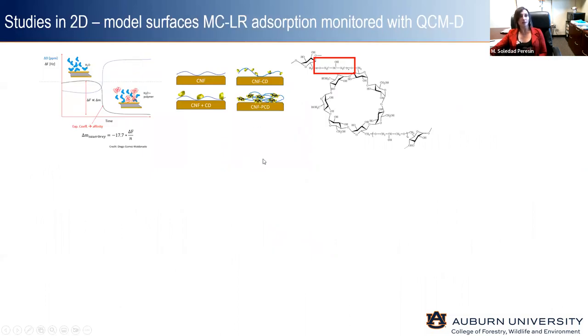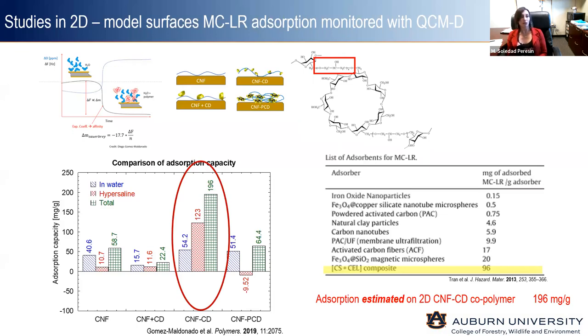So what we did was several assemblies. In this case, we started, as everything starts in our lab, in the two-dimensional state. We created these self-assembled model films of nanofibrillated cellulose, and we assembled the cyclodextrin in different ways. We adsorbed it onto the nanocellulose, but also we grafted it onto the cellulose nanofibers. We monitored the adsorption of this microcystin LR onto these different systems, and what we noticed was that the cyclodextrin grafted nanofibrillated cellulose showed the most adsorption onto the material.